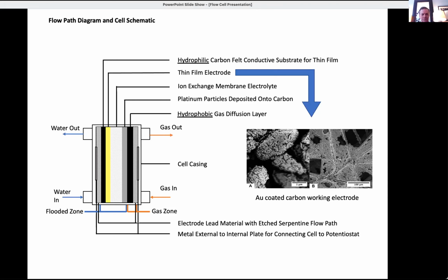rate supply of hydrogen to keep the potential on this electrode during the stripping experiment constant, so that we have a good reference here. So we have a very simple cell configuration with a setup which generates its own reagent for the reference electrode, which is hydrogen. It gives the ability to regenerate the membrane if the membrane starts to get fouled with other ions. And it gives us the ability then to perform stripping voltammetry on our ultra low loading gold thin films.